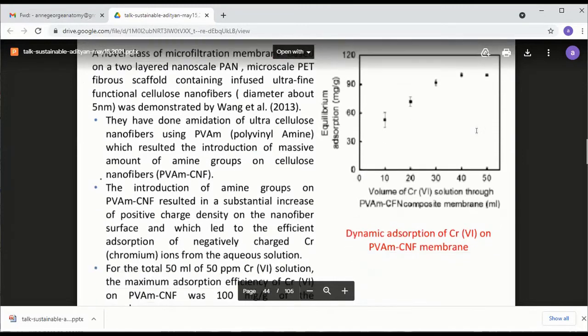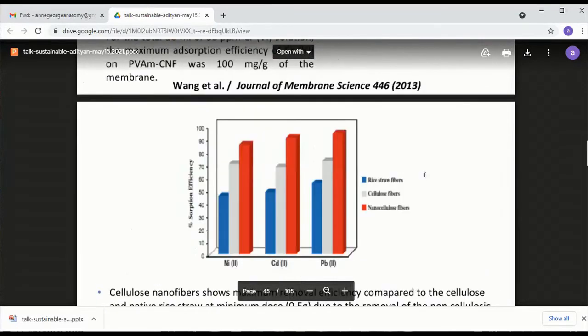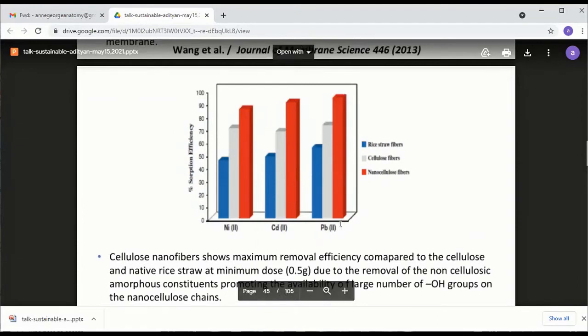So if you make the surface of nanocellulose electropositive by introducing amine group, you can see the adsorption equilibrium of chromium. Beautiful adsorption of chromium. So you can remove chromium. You can also remove nickel, cadmium, lead. The only thing is you do the required surface chemistry. So we are able to remove all sorts of metallic impurities from water.